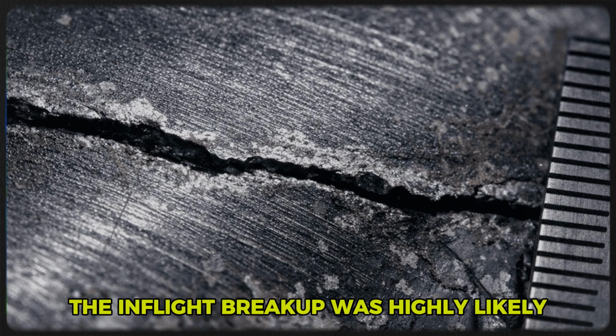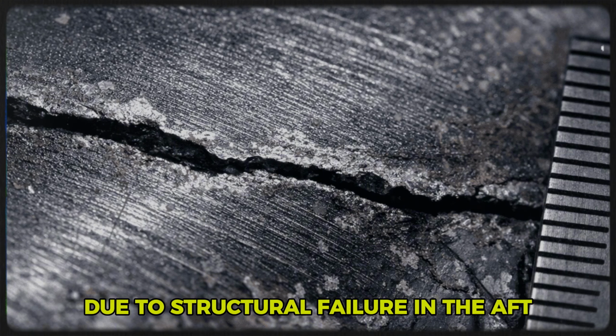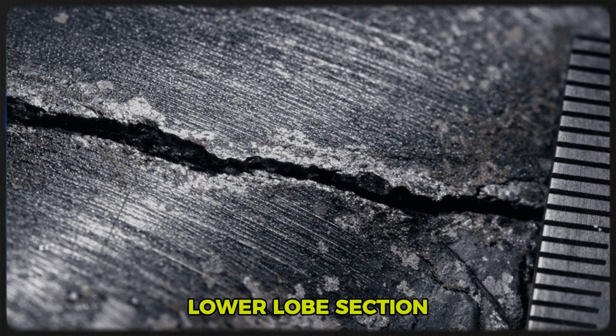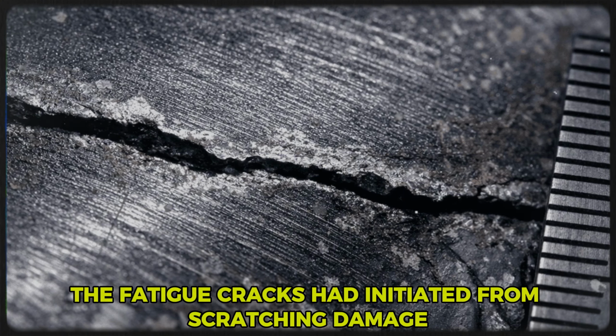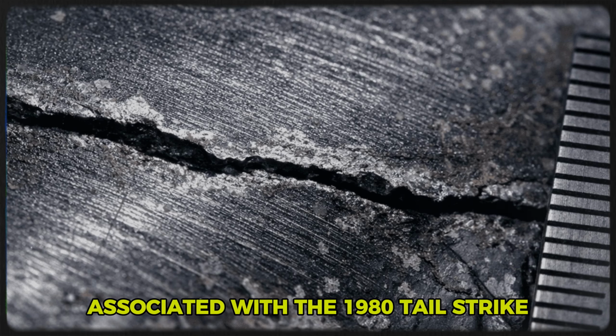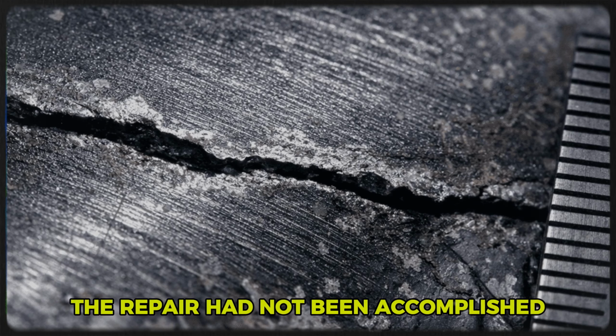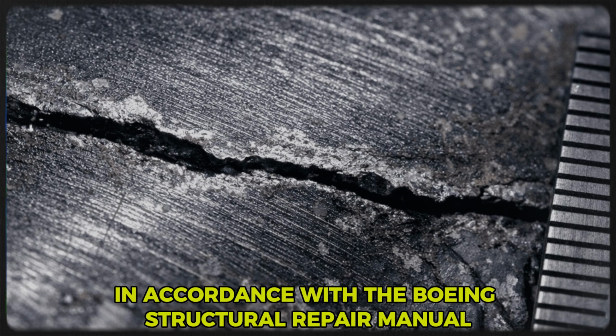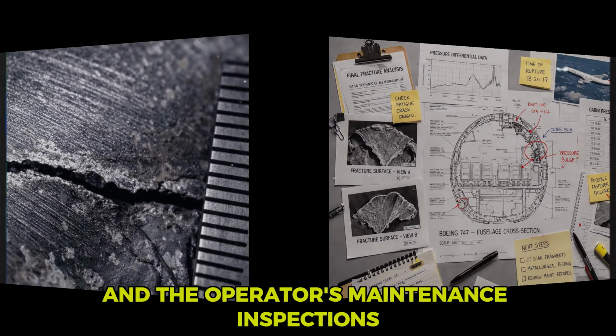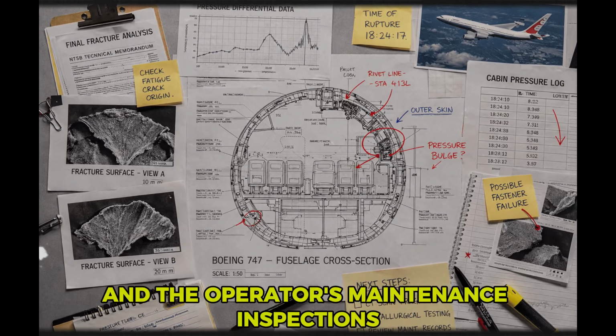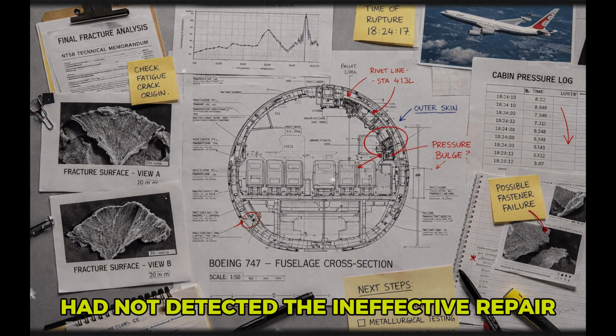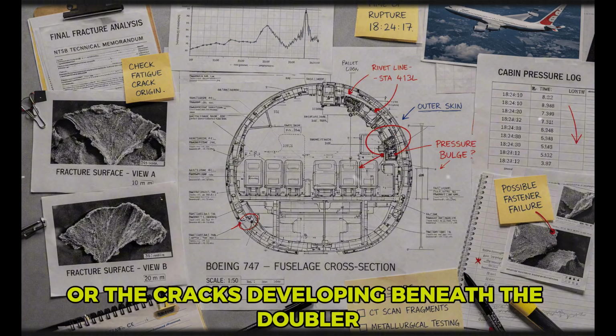The in-flight breakup was highly likely due to structural failure in the aft lower lobe section. The fatigue cracks had initiated from scratching damage associated with the 1980 tail strike. The repair had not been accomplished in accordance with the Boeing Structural Repair Manual, and the operator's maintenance inspections had not detected the ineffective repair or the cracks developing beneath the doubler.